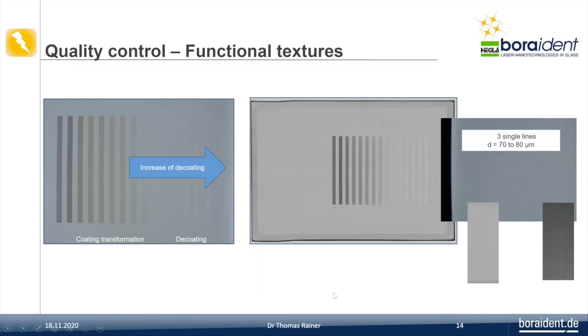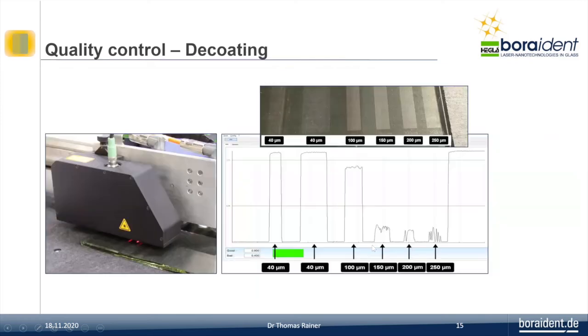And if we do so, then we have to control it. What we have is an optical scanning system where we see what happens, the removal or the modification of the coating, and it's a very good quality control. Then we use sensor systems to see if a removal is full or not. You see here the example with a coated glass with different stripes, and these are the sensor signals. You see the first stripes are very good because they are over this green line, and the other looks similar, but this sensor signal says it's bad from the removal here.